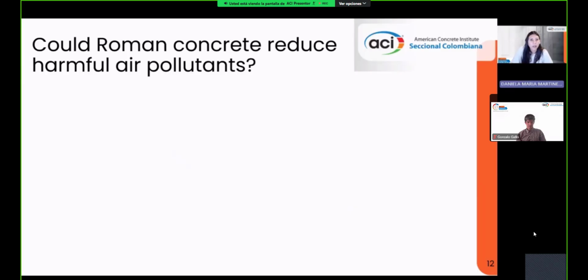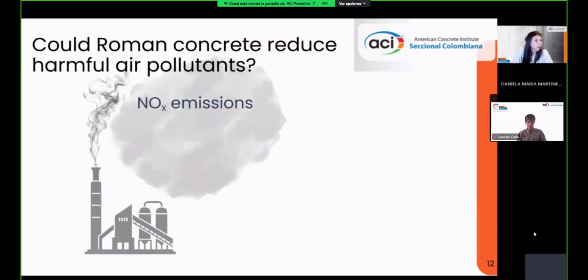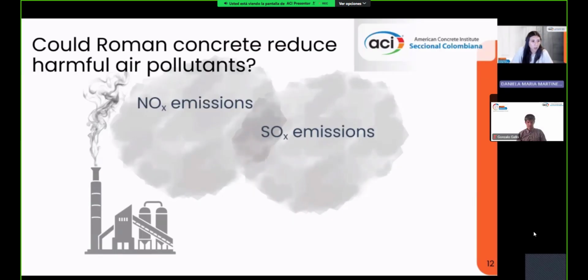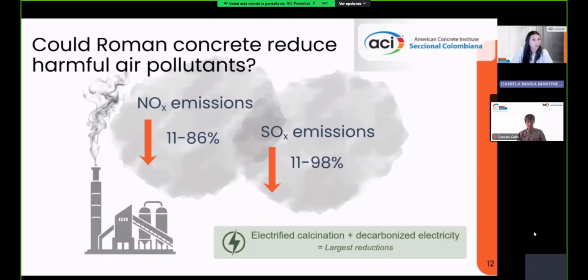Now, while Roman concrete did not consistently reduce greenhouse gas emissions, it did show significant reductions in other air pollutants, which are precursors to compounds that can be harmful to human health. So when we look at estimates on nitrogen oxide and sulfur oxide emissions, or NOx and SOx, we see a big reduction compared to modern concrete production, all the way from 11% to 98%, depending on the production scenario that we were analyzing. So these benefits were observed across fossil fuel, biomass, and electrified production pathways, of course with the largest reduction when we model electrified calcination of limestone using decarbonized electricity. Since NOx and SOx contribute to air pollution and adverse health impacts, these Roman-inspired formulations may offer benefits beyond carbon reduction or embodied carbon.